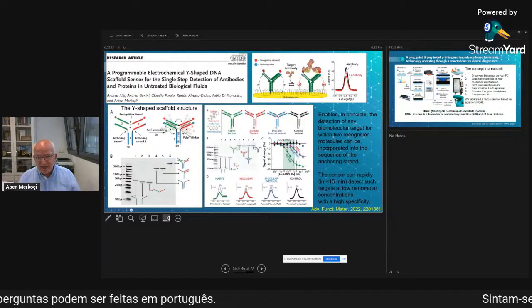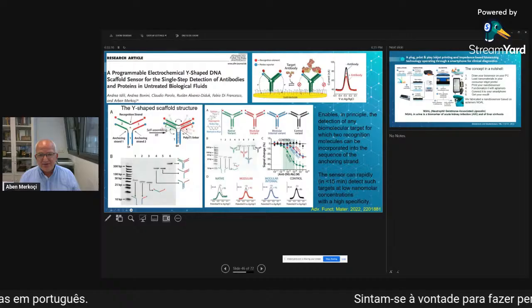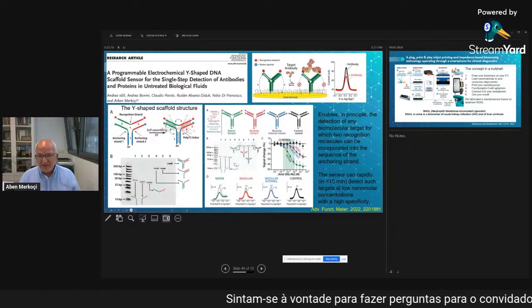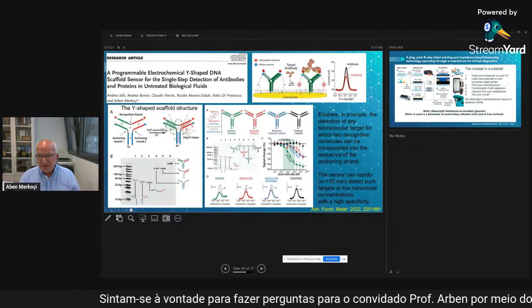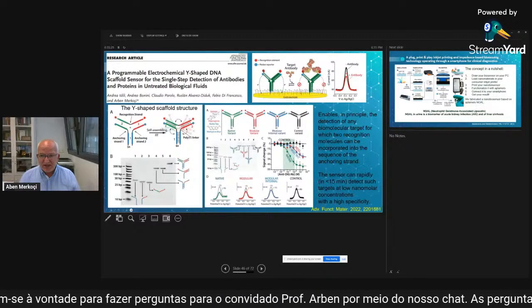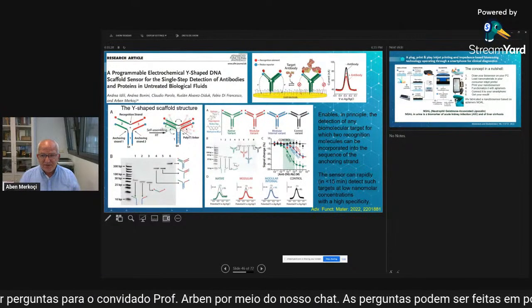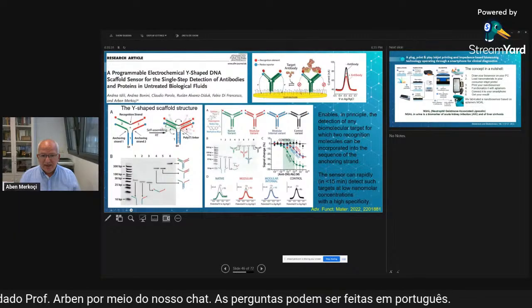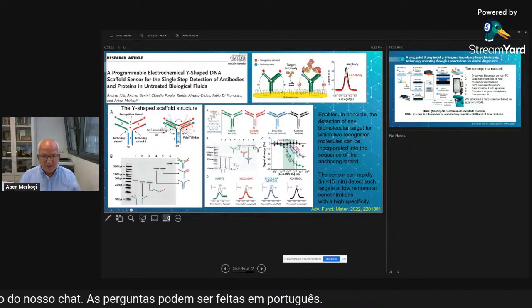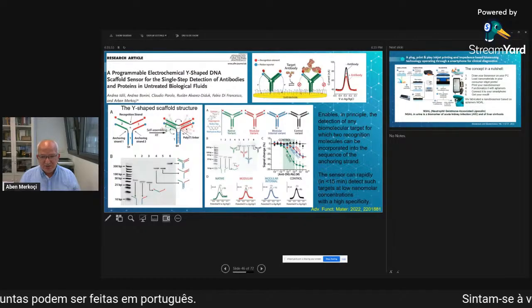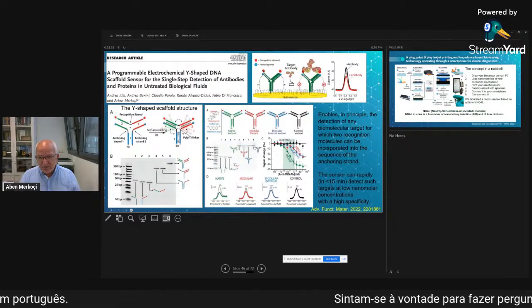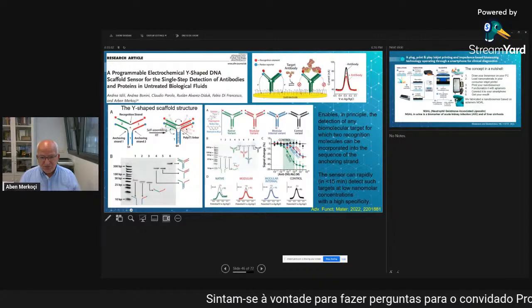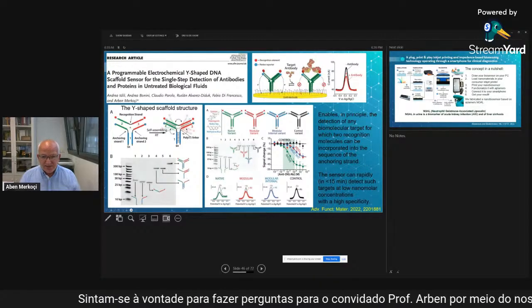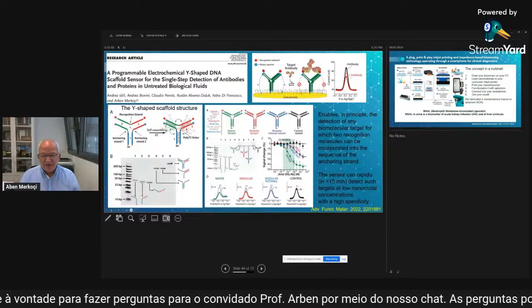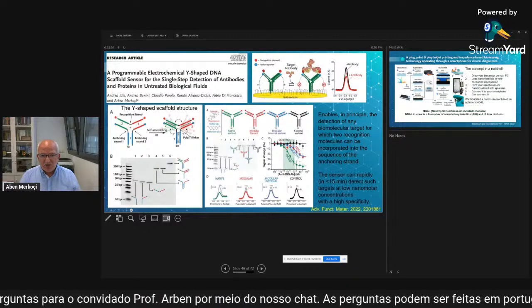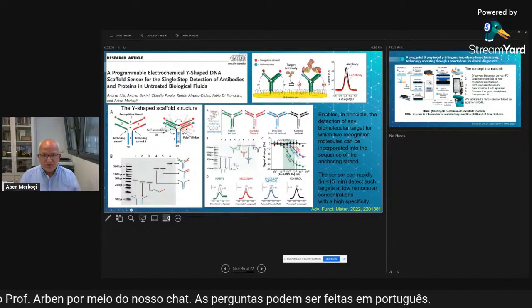You can see that again, this Y-shaped DNA with the redox reporter is changing conformation, and we can detect the change of the current based on the interaction of this Y-shaped DNA with the target antibody. After doing the measurements and controlling native and modular variant with internal control variant, we are able to measure the concentration of the antibody with very, very high sensitivity based on the changes of the signal coming during this interaction of this electrode, the gold electrode used for this case.